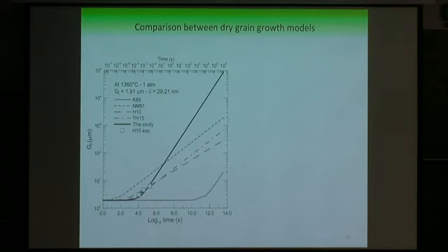And so as you can see, these two curves here that correspond to Hiraga's and Tasaka and Hiraga's model do well reproduce these experimental grain sizes, whereas the grain growth equation from Karato shows really slow and almost null grain growth until high duration. And Nichols and Mackwell seem to exaggerate the grain sizes.